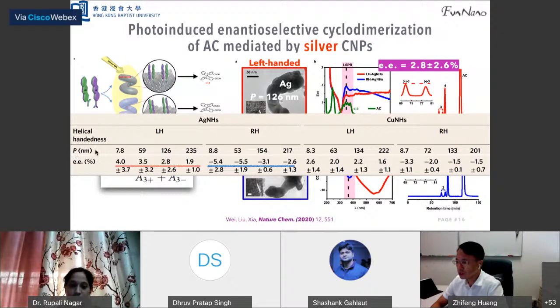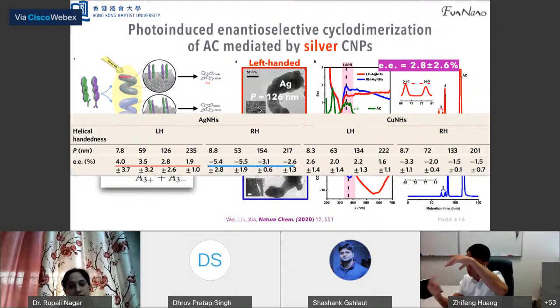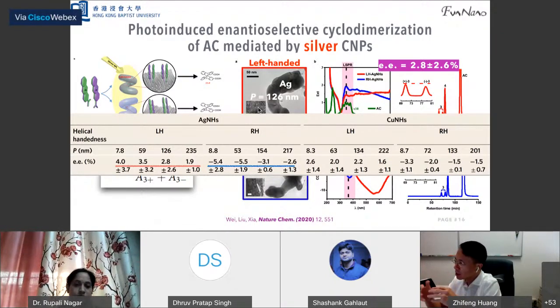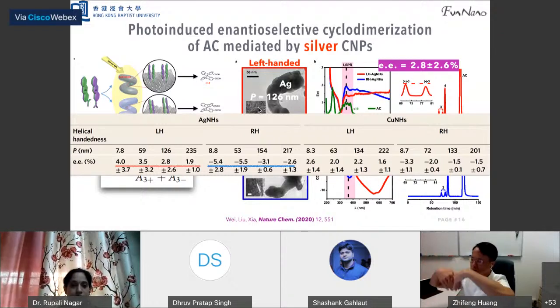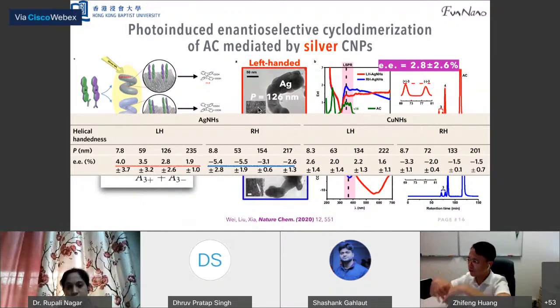Actually, if we consider the pitch, for example, 230 nanometer, right? This helical structure is very big, which will not be visible by the molecule. But when you zoom into these surfaces, they have a chiral lattice, because we rotate the substrate when we do the growing. So this chiral phenomenon is actually at the atomic scale, and so we can control the adsorption format of the molecule.